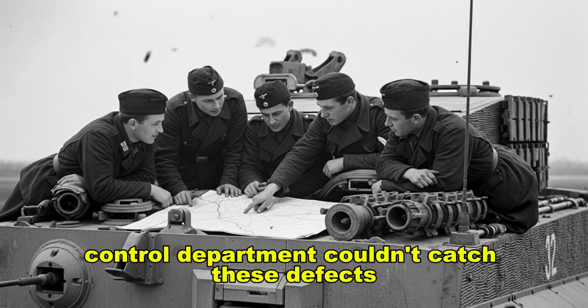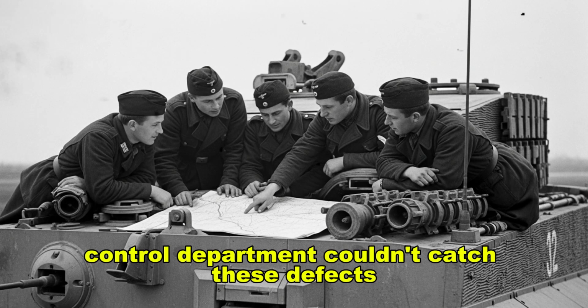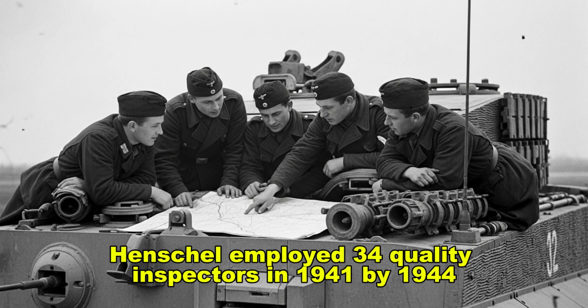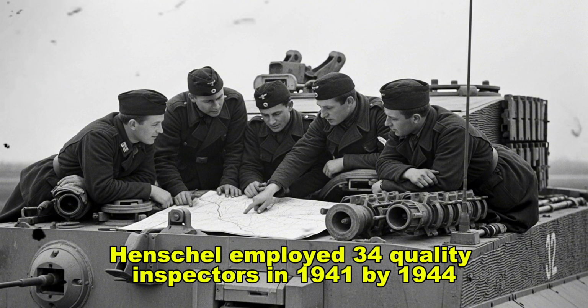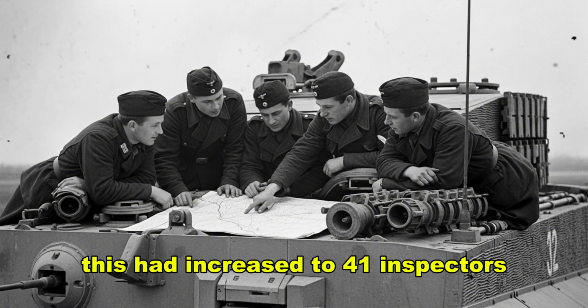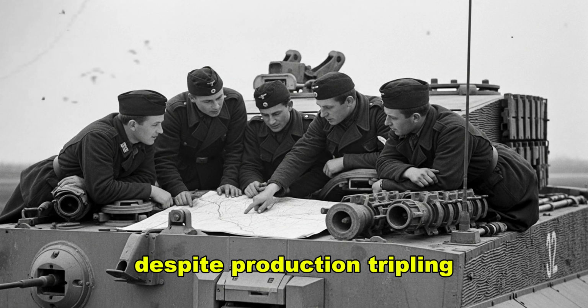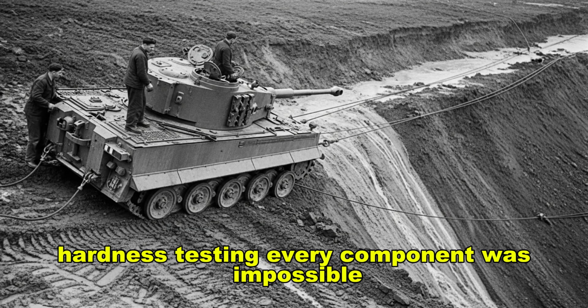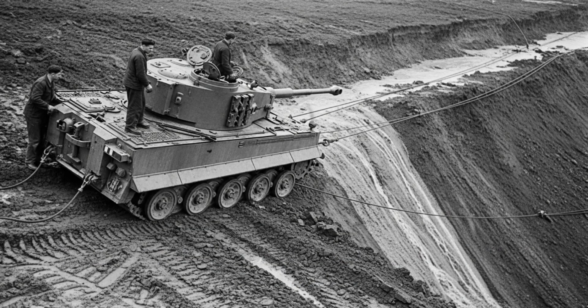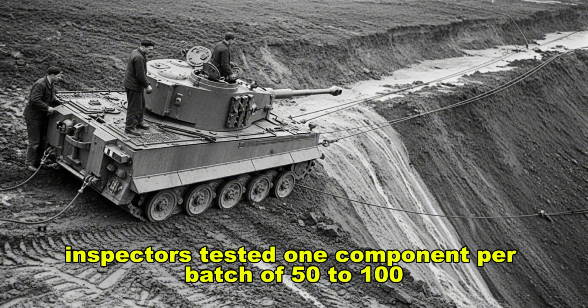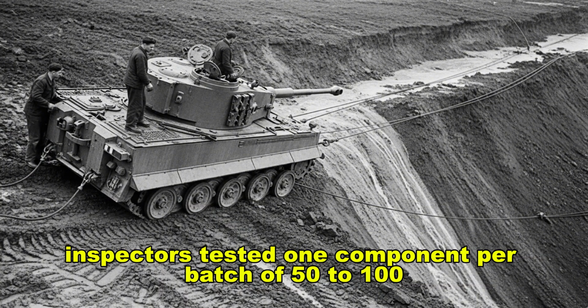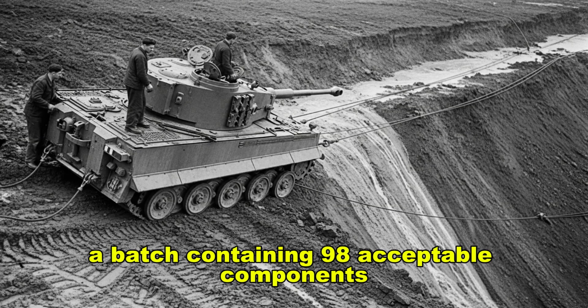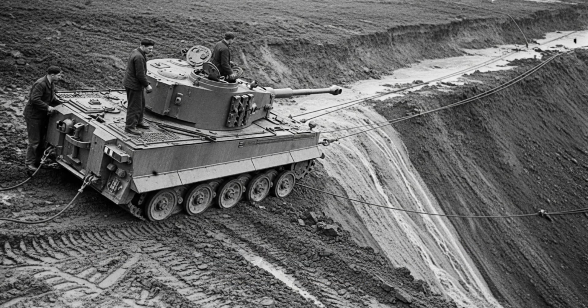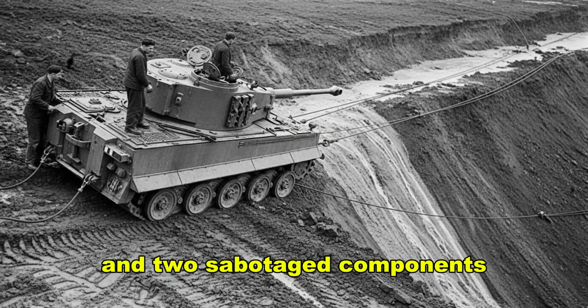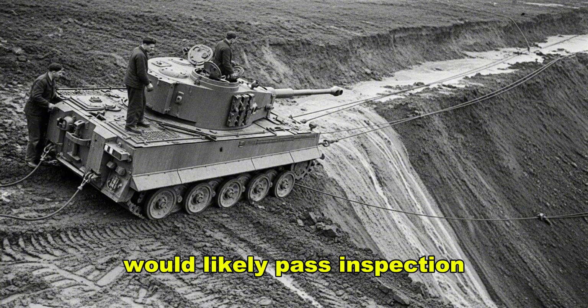The quality control department couldn't catch these defects. Henschel employed 34 quality inspectors in 1941. By 1944, this had increased to 41 inspectors despite production tripling. Hardness testing every component was impossible. Inspectors tested one component per batch of 50 to 100. A batch containing 98 acceptable components and 2 sabotaged components would likely pass inspection.